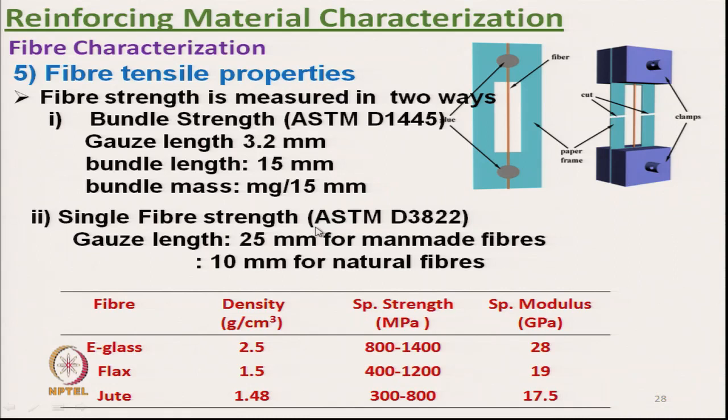we can also perform the single fiber strength test, and the gauge length here is 25 mm for man-made fiber and 10 mm for natural fiber. Okay.